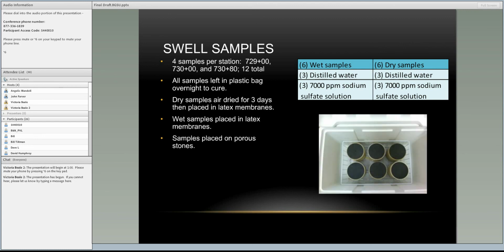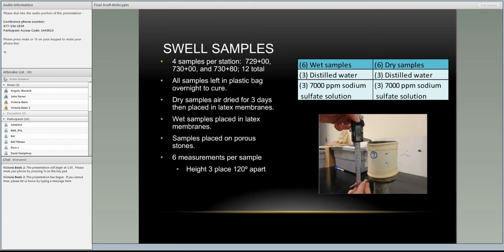And there were 6 measurements taken per sample, 3 for height, 120 degrees apart. You can see the markings on the top of the porous stone there that we used. And then 3 for circumference, 1 at the top, middle, and bottom. And then these 3 measurements for each one were averaged and used to calculate the volume change of the sample. And the measurements were taken every day for each sample for 56 days.